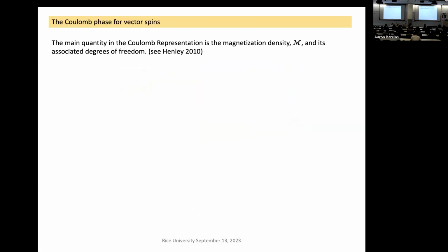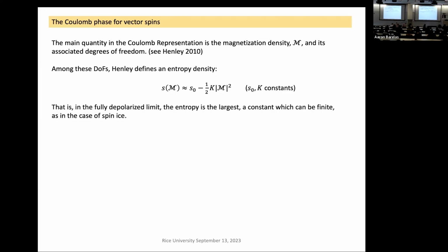The main quantity in the Coulomb representation is the magnetization density and its associated degrees of freedom. One of the key relationships, at least for me, is that the entropy goes down as the magnetization goes up, which is the opposite of what happens in an antiferromagnet. If you put a field on an antiferromagnet in its ordered state, the magnetization goes up, obviously, that has to happen. But the entropy goes up also, because you transfer the degree of freedom, so there's more entropy. So this is a testable thing. It's already been tested. I'll show you.